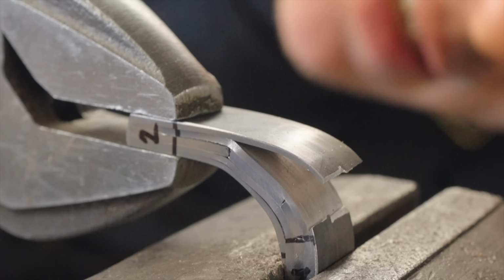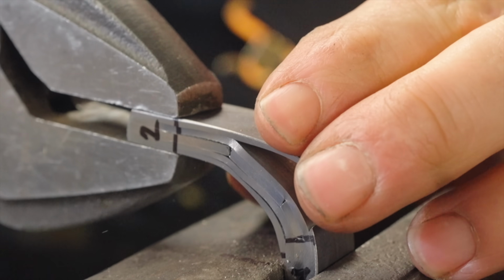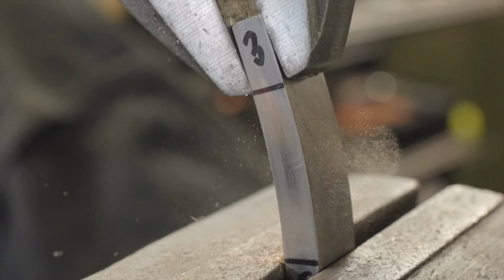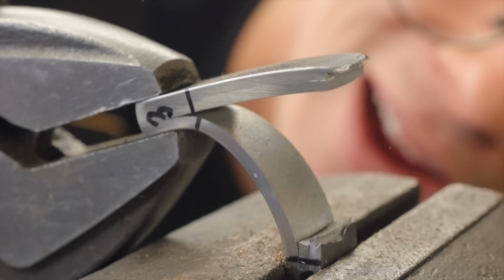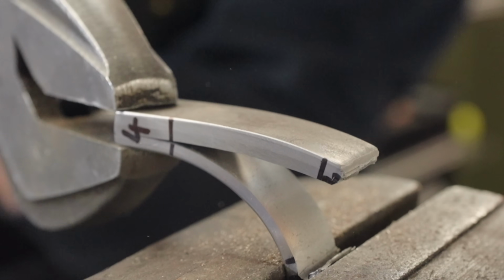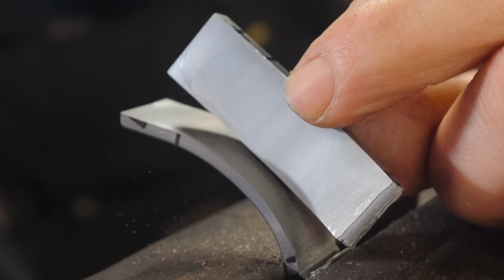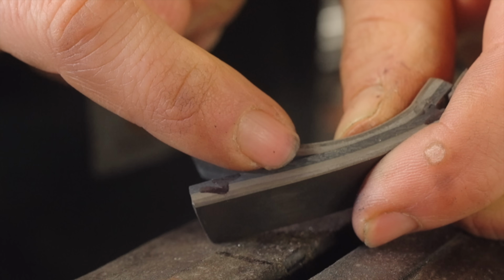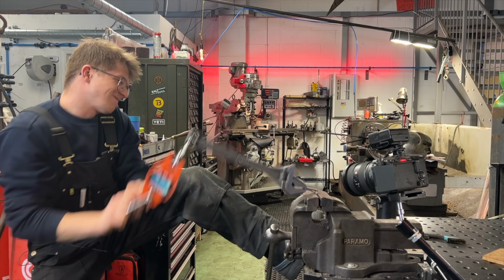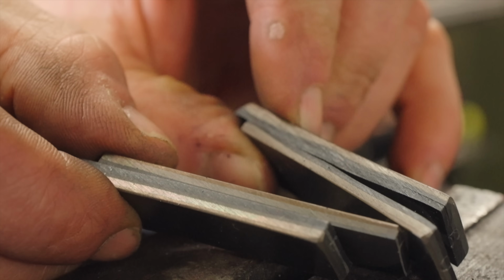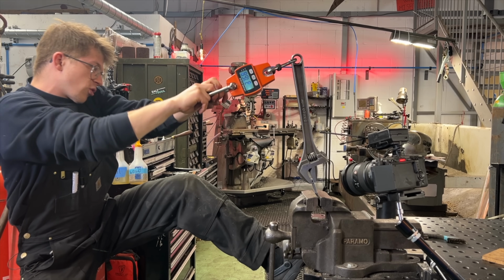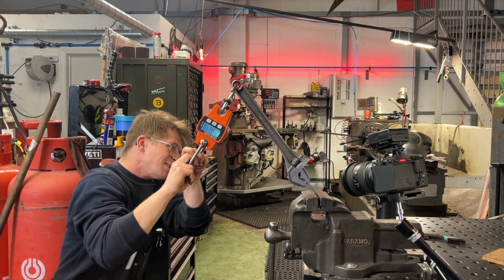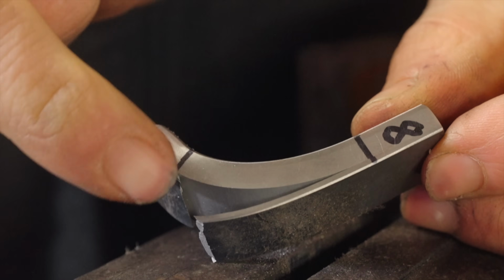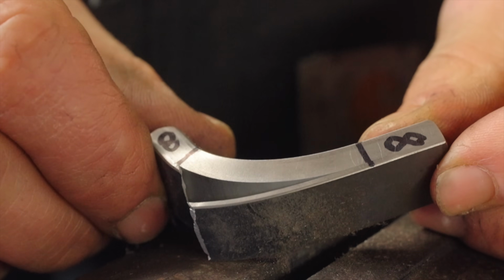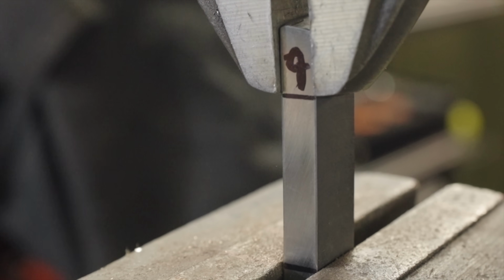Oh, broken the titanium. Oh, there's plenty of delamination though anyway. Madness. Oh, that was bad. No longer attached. That was a delamination between the nickel and the steel. Poor thing. We're obviously not doing 6 and 7. 8, our titanium control. Broke at the grade 5, grade 2 interface. 9, our steel control.